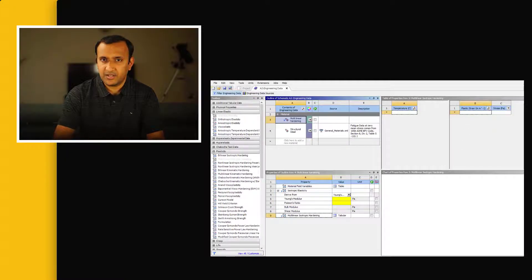Now, one may ask, why we go through the trouble of inputting plastic strain versus stress instead of total strain versus stress? This allows us to define both effects independently, which is useful if we have different temperature-dependent data sets for elastic modulus compared with plastic strain-stress. If we define total strain versus stress, we have redundant data point with elastic modulus at yield, and we cannot resolve the difference if values are inconsistent. Therefore, we separate material definition into elastic and plastic behaviors.